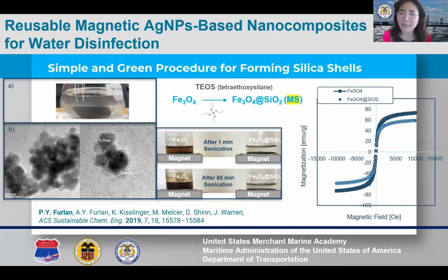To address the first concern, we enhanced the magnetite's stability against oxidation by coating magnetite nanoparticles with a silica layer, forming MS nanoparticles. Unlike the typical Stöber method using tetraethoxysilane, or TEOS, as the silica source, with ammonia, varied alcohols as solvents and binding agents, often at elevated temperatures, we introduced a greatly simplified and green approach. For the first time, we utilized water as the sole solvent in the Stöber process to achieve silica coating on magnetite nanoparticles under ambient conditions, eliminating the need for alcohols or stabilizers.